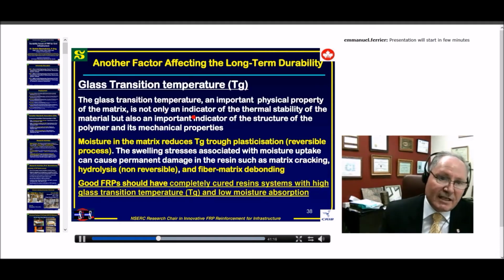Glass transition temperature is really a thermal property which is extremely important. We can measure it with DSC or with DMA. We have ASTM standards for both methods. Either way, it gives a very good idea about the long-term stability of the resin, and by investigating the glass transition temperature, we can know more about the behavior of the resin.